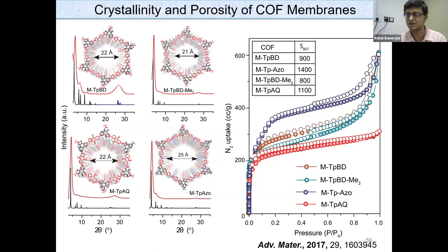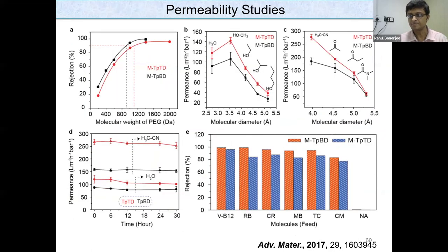Please note that this is not a powder. You take the film, you do a gas adsorption analysis without doing anything, and you will get this nice porous internal crystalline structure of the films itself. We have not done any grazing incidence. This is a Bragg-Brentano geometry. So their crystallinity is very nicely ordered throughout the X, Y, and Z axis.